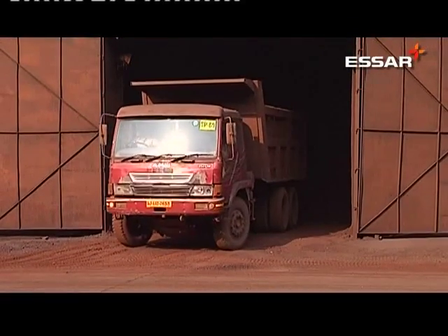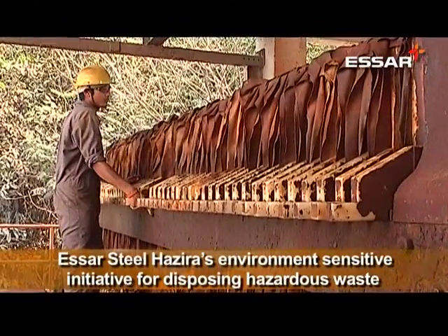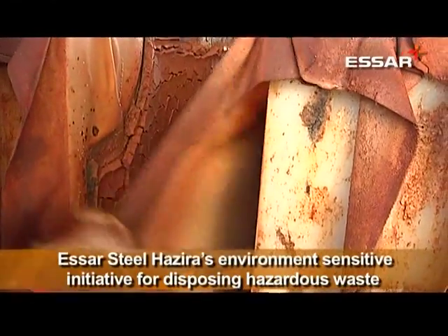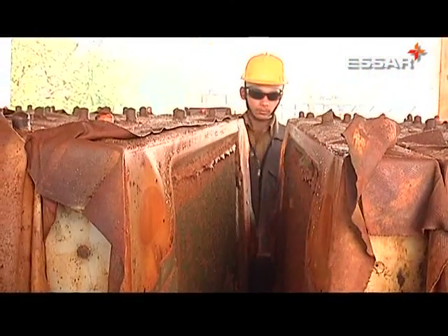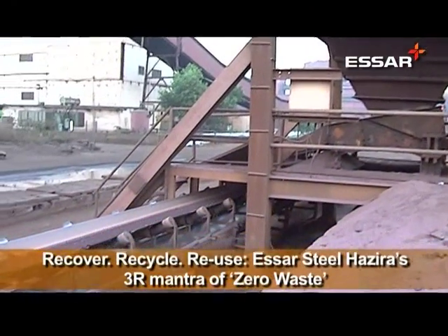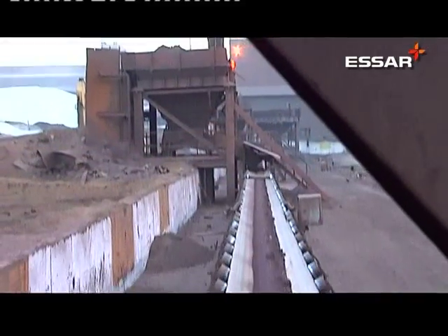Following a synchronized process, dust micro-pellets from the steel melt plant fume extraction system are transported to a specially set-up facility in the CRM sludge dumping area. Here, the iron-bearing waste from the FES is mixed with the sludge and lime, which are added as a binder. The mixture is fed into a simple rotating drum or drum pelletizer and transported to the material handling yard, where it is fed by a conveyor to the sinter plant.